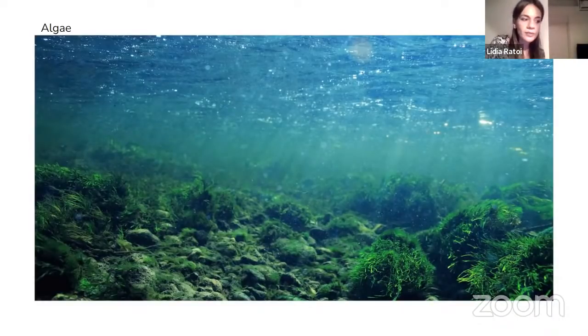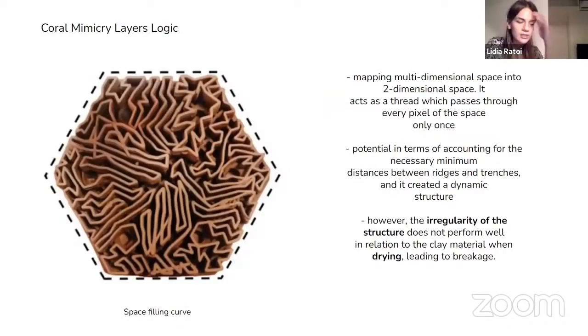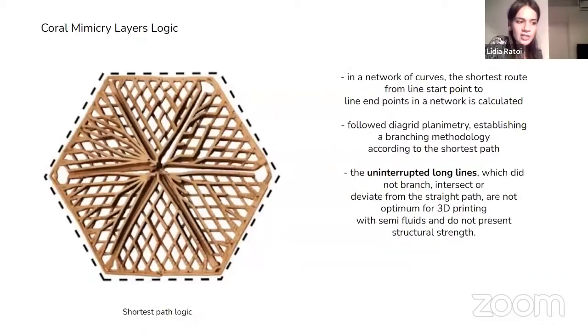So we started with a space filling curve, but it was irregular. So that created problems when it was drying, it was cracking. Sharp edges also are not good because they would interfere with coral growth patterns. So you really had to accommodate for how the corals naturally grow. So then we tried a shortest path logic, but again, there were long lines uninterrupted. So they were cracking when they were drying.